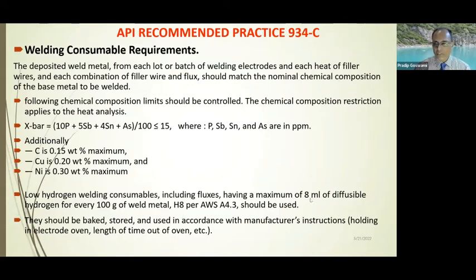And low hydrogen welding consumable, typically H8 type is the bare requirement, but H4 is most common, which most of the manufacturers are able to give for SMAW, and GTAW has even lower than that, or it's absolutely nil if you go that way. FCAW welding consumables, meeting the H4 grade is often difficult, so H8 is the bare minimum, and the same applies for the submerged arc welding consumable also.